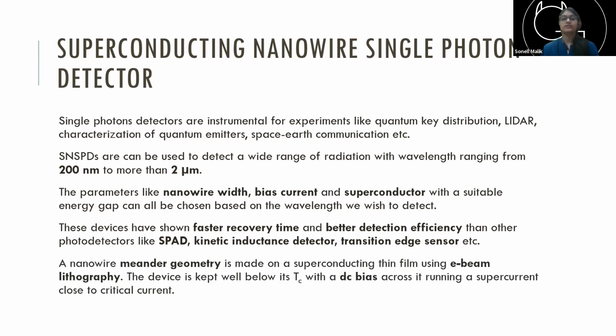The SNSPDs are usually made in the meander geometry that I showed you, and you can make that using electron beam lithography. The device is kept at a DC bias. Superconductors have a critical current density. If you pass a current across a superconductor above a certain value, it will become a normal conductor. So what we do is we have a current running through our SNSPD just below the critical current. If IC is the critical current, we pass about 97% of IC through the superconducting nanowire single photon detector.